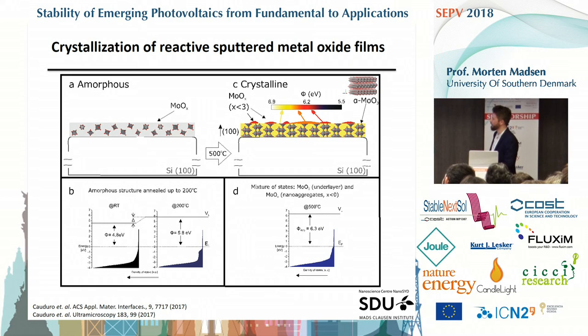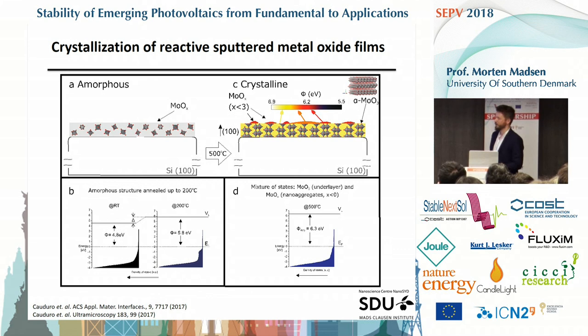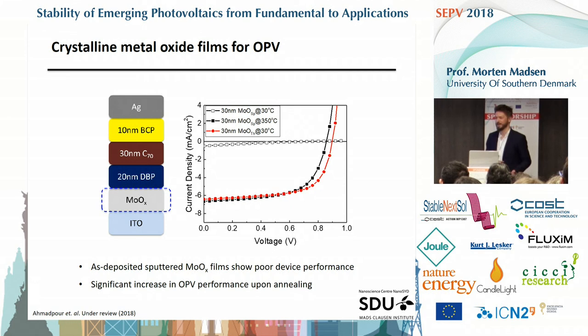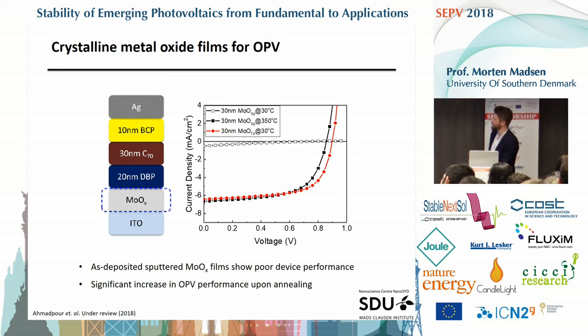These studies on silicon were done and published last year. For devices, of course, we would have to embed them directly on ITO surfaces. Our next work was to make devices from these. We formed this kind of device stack: ITO as the transparent conductive electrode, molybdenum oxide on top from reactive sputtering or from thermal deposition as a reference device, and then on top we evaporate a small molecule—DBP:C70 as the active layer mixture—and then BCP/silver as the top contact.